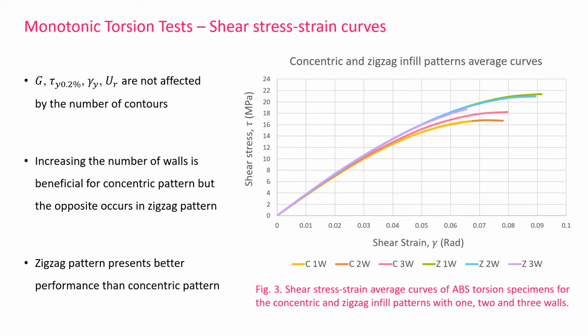In concentric pattern, ultimate shear strength, fracture strain, and toughness modulus increase with increasing the number of walls, but the opposite occurs in the zigzag pattern, leading to a decrease in both ductility and strength. Overall, the zigzag infill pattern presents better performance than the concentric pattern.